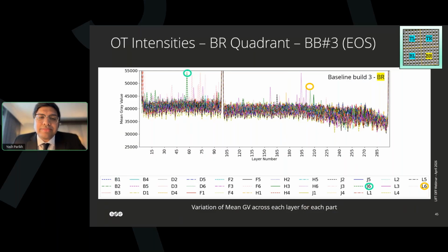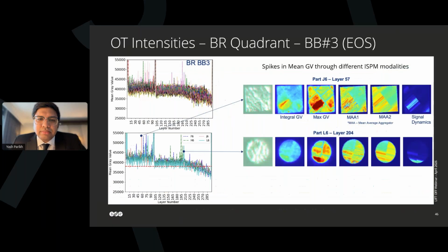What we found out is that they correlate to defects. J6, L6 were looked at closely for all modalities. For integral GV, max GV, I said, no, don't believe in mean gray value. Just give me an integral value. Give me a max value, moving average value for 1 layer, moving average for 2 layers, moving average for 5 layers, signal dynamics. You really probe that and you see that, okay, that's exactly what it is. It is not just an anomaly. It is at that point that the mean gray value is flickering, because of what we discussed. Go to the next one.